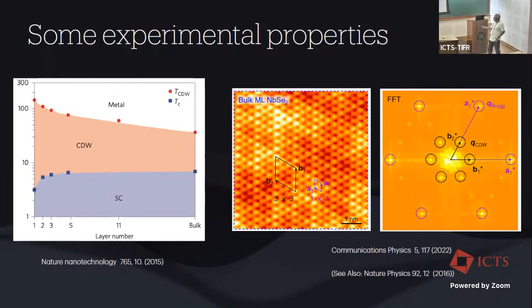Now, this is the typical phase diagram as a function of layer number that is shown by this material. If you now look at the CDW phase, the nature of the charge density wave in this system is a structure which shows a 3Q charge density wave order. That means essentially there are three ordering wave vectors, 1, 2, and 3, which are related to each other by 60-degree rotations. And if you Fourier transform...